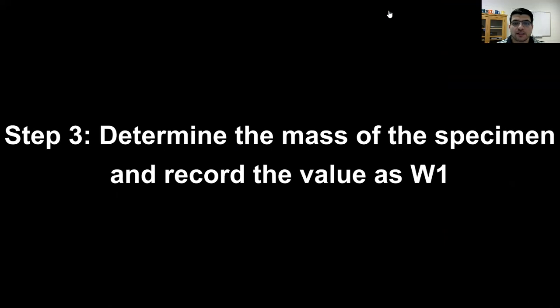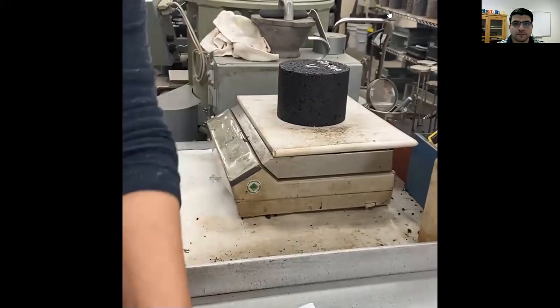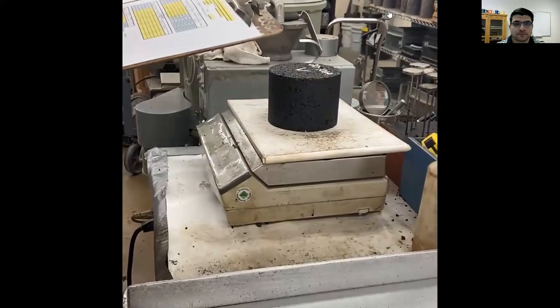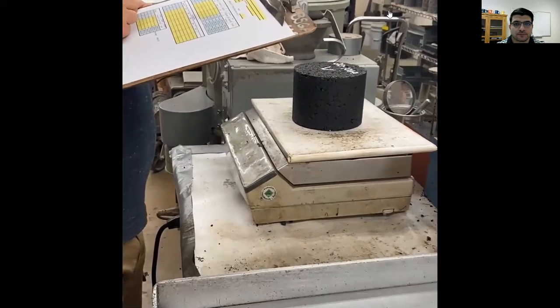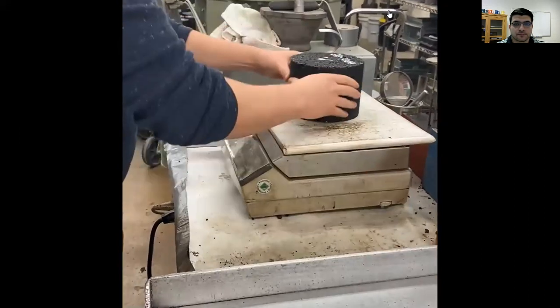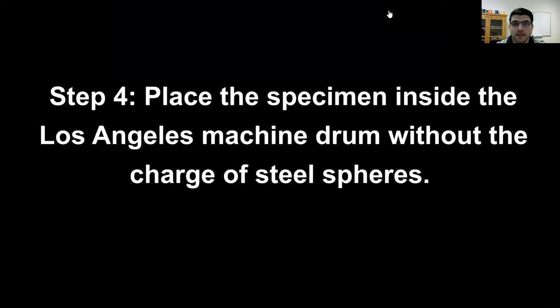Step 2 continued: the specimen shall remain at the test temperature for at least four hours. Step 3: determine the mass of the specimen and record the values. Step 4: place the specimen inside the Los Angeles abrasion machine drum without the charge of steel spheres.